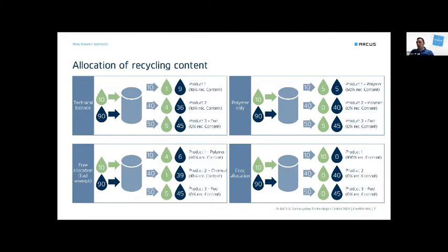The second option is again a free allocation, but with the exclusion of fuel production. You take everything of the yields out of pyrolysis through cracking, going through the steam cracking unit, which then produces monomers for plastic production, but also chemicals production. So again you have up to 50% of total recycling content distributed into a polymer or into chemicals. We, as Chemical Recycling Europe, consider the free allocation with fuel exclusion the most suitable, since chemicals are also important, not only plastic. That is currently our position.